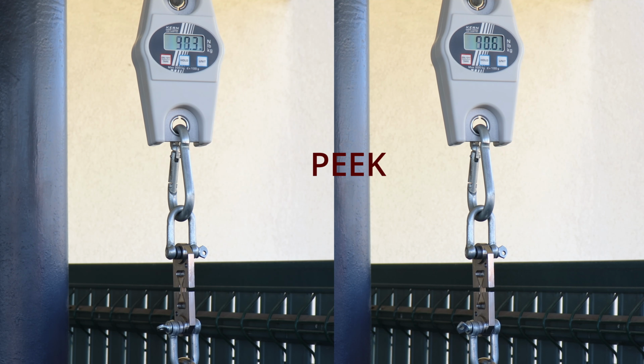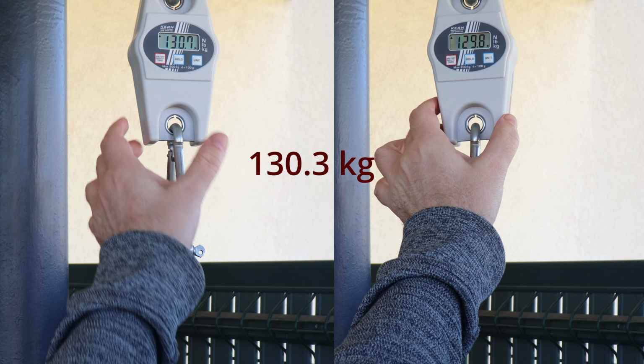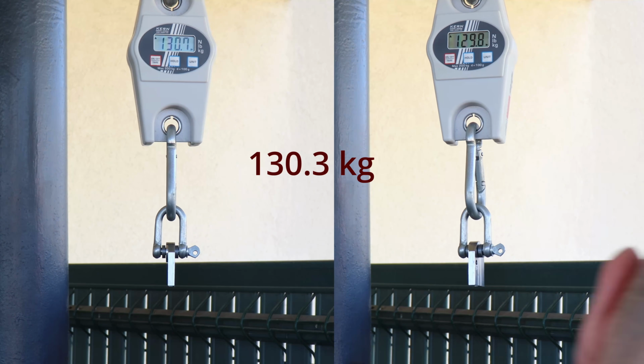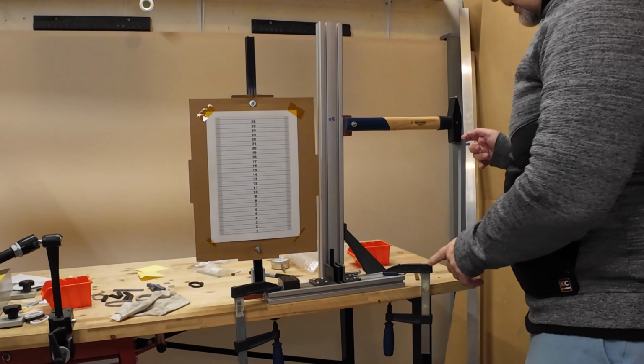And now the PEEK. This is strong, but I already tested several regular materials with this strength. Now actually I checked my summary table for my Patreon supporters, and I found 5 materials which are stronger than this value, but this is resin and this is CNC machine nylon, so only 3 FDM materials are stronger than this PEEK. And now the impact test.